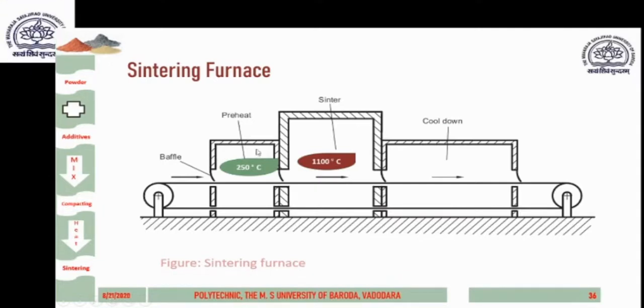For example, if a preheating of 40 minutes is required, and the speed of the belt is 1 meter per hour, then what would be the length of this preheat? It would be around 1 or 1.5 meters long, because the part comes in at room temperature. It requires some time to get up to 250 degrees centigrade, and thereafter the complete part is to be soaked at 250 degrees centigrade for 40 minutes, say.